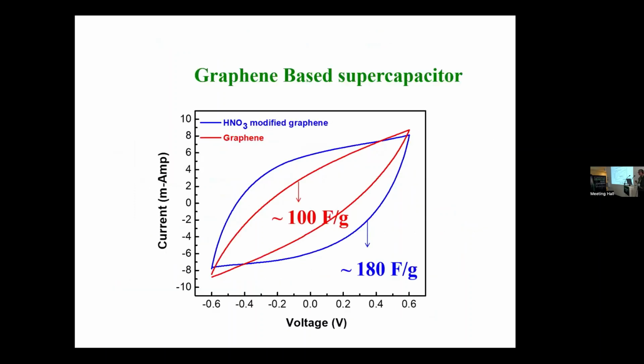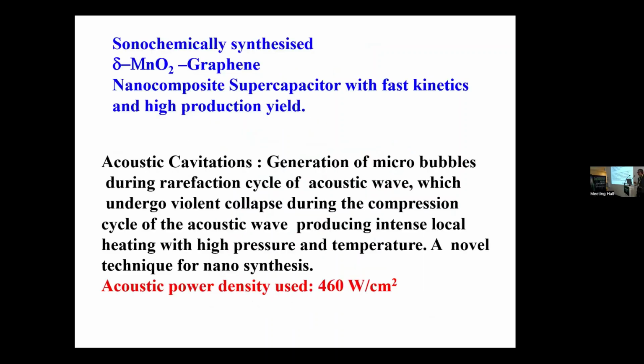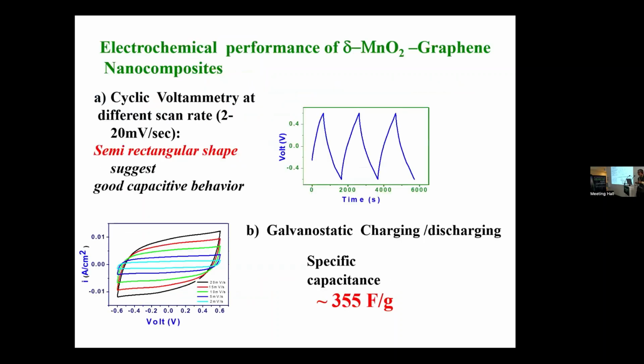Then we did some work on graphene-based supercapacitors. When graphene was modified with nitric acid, its capacitance increased to 180 farads per gram. Also, we worked on some sonochemically synthesized materials. Sonochemistry is a fairly new technique nowadays, where instantly, because of the rarefaction and compression cycle, a huge power density and huge temperature are generated, which can be employed in synthesizing nanoparticles by breaking the molecules. So with the delta MnO2 and graphene nanocomposite supercapacitor, we got a capacitance value of 355 farads per gram.